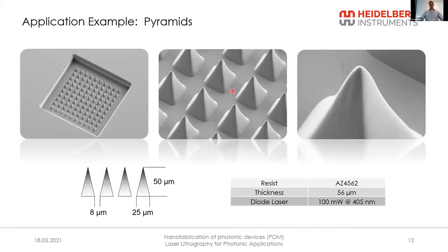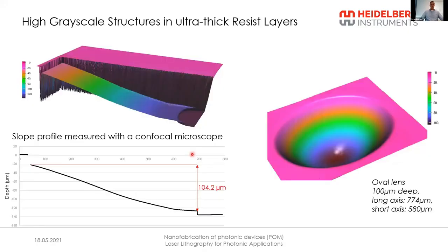Most of the grayscale applications work in the resist thickness range of maybe up to 20 or 30 micron, but there's always some applications that would like to go thicker, like in this case, we exposed some pyramids in 56 micron thick AZ4562. And that's pretty much the limit of the thickness that can be exposed so far. The thicker the resist, the more difficult it is to get uniform resist slopes, and also the process is more demanding.